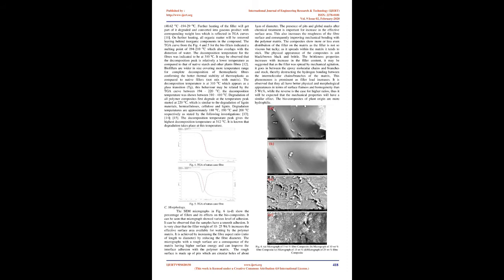Further heating of the filler will cause part of it to degrade and convert into gaseous product with corresponding weight loss, which is reflected in the TGA curves [11]. On further heating, all organic matter will be removed, leaving behind inorganic components in the compound. The TGA curves in Figures 4 and 5 for the biofillers indicated a melting point of 194 to 210 °C, which also overlaps with the evaporation of water.